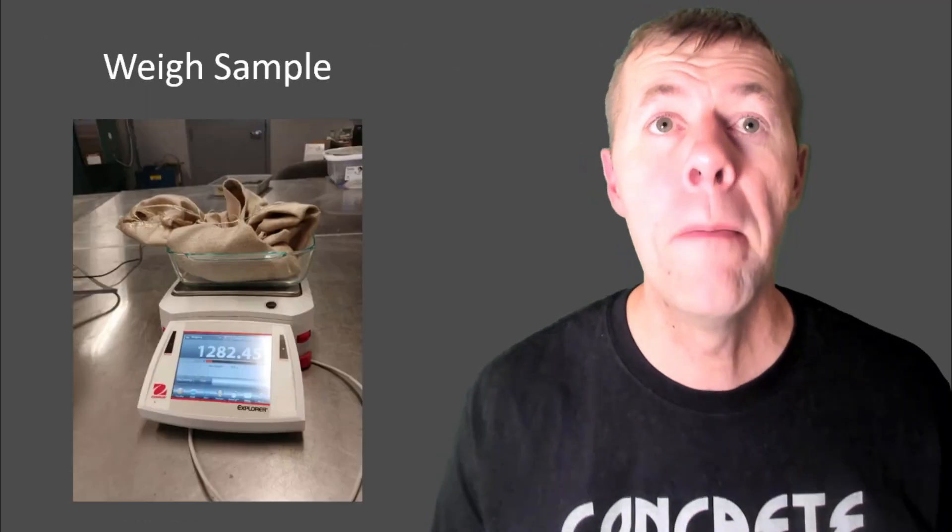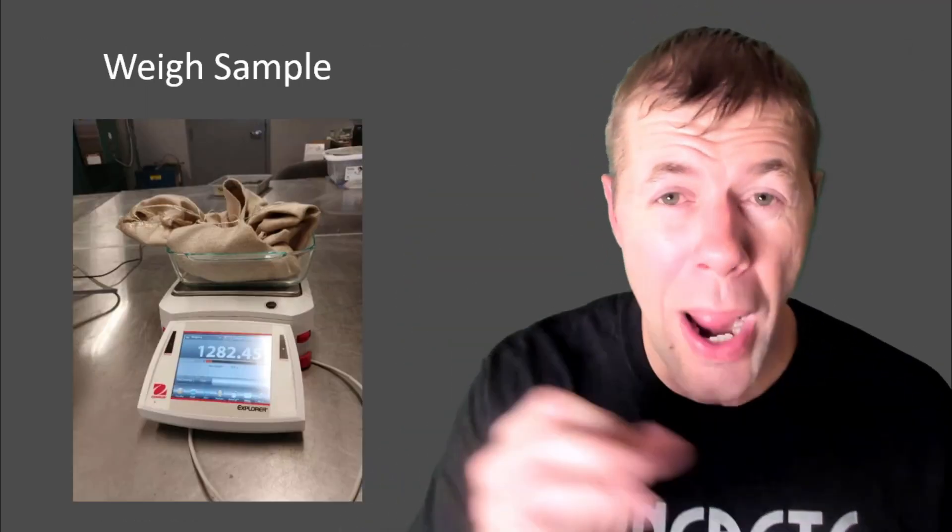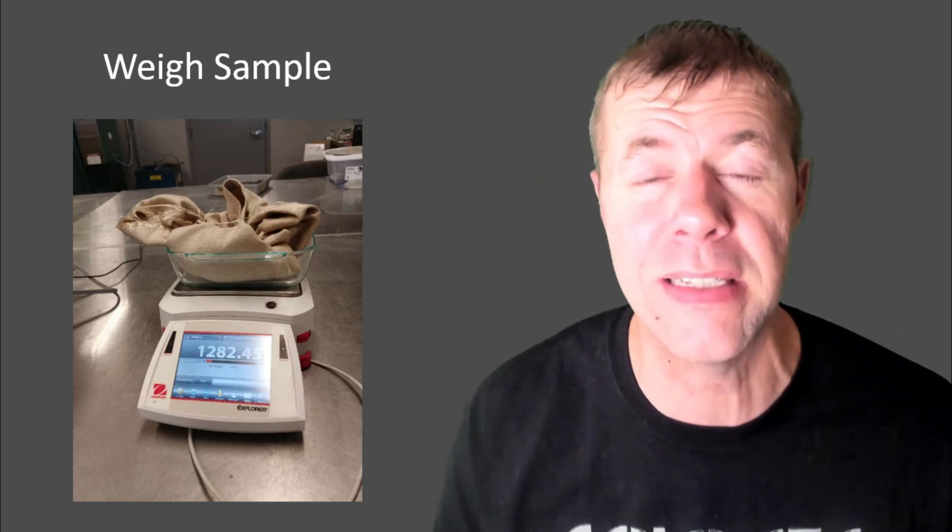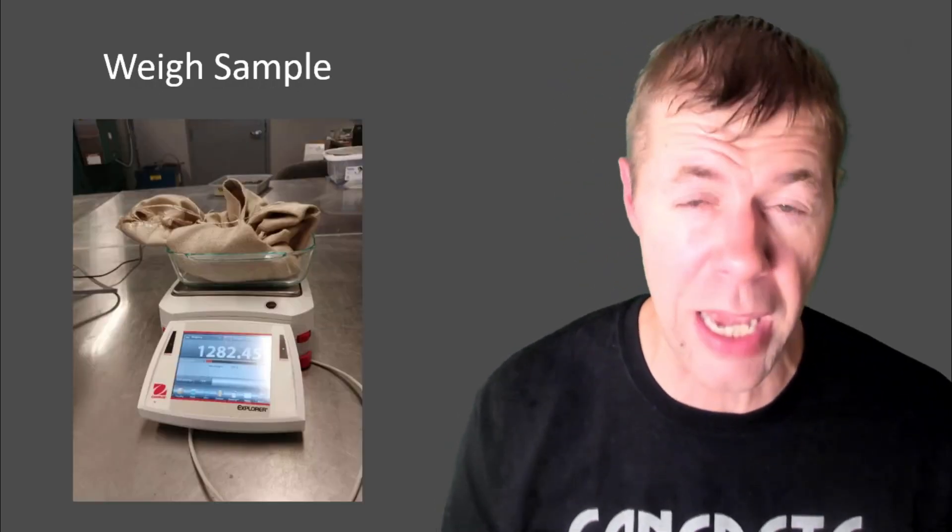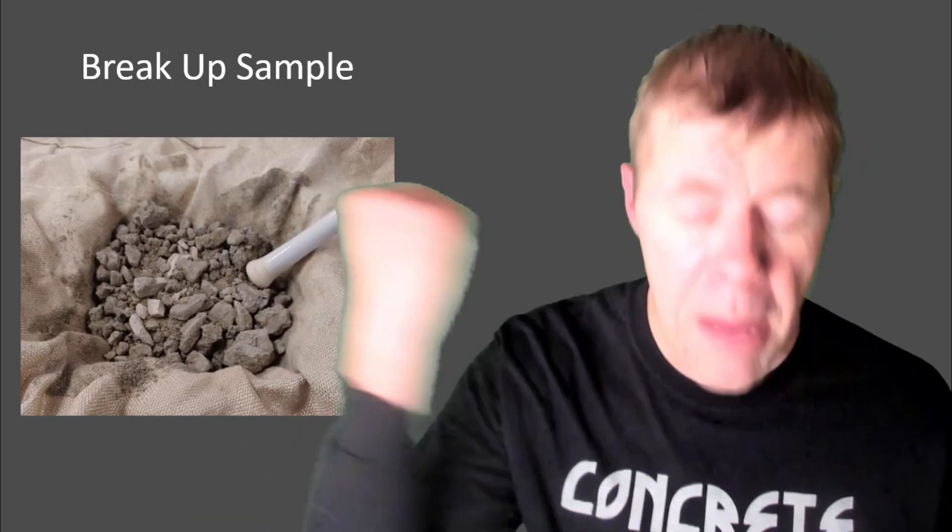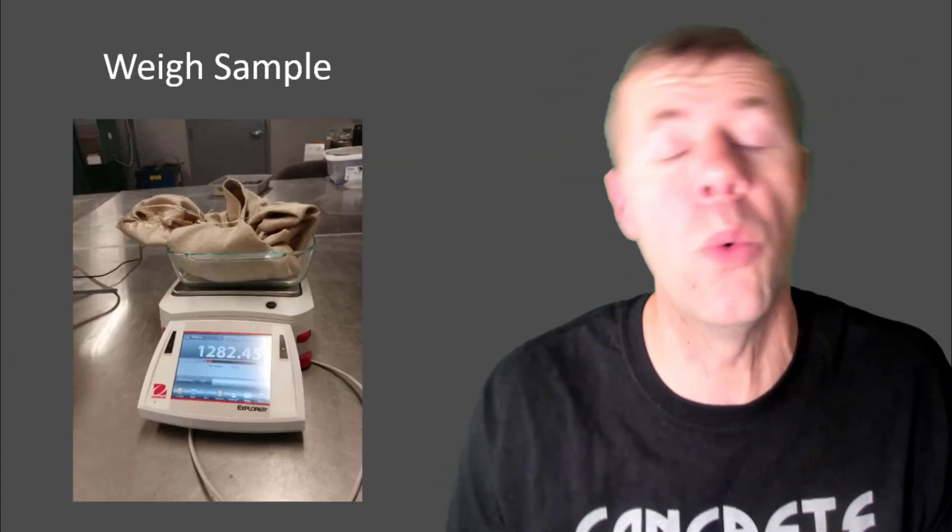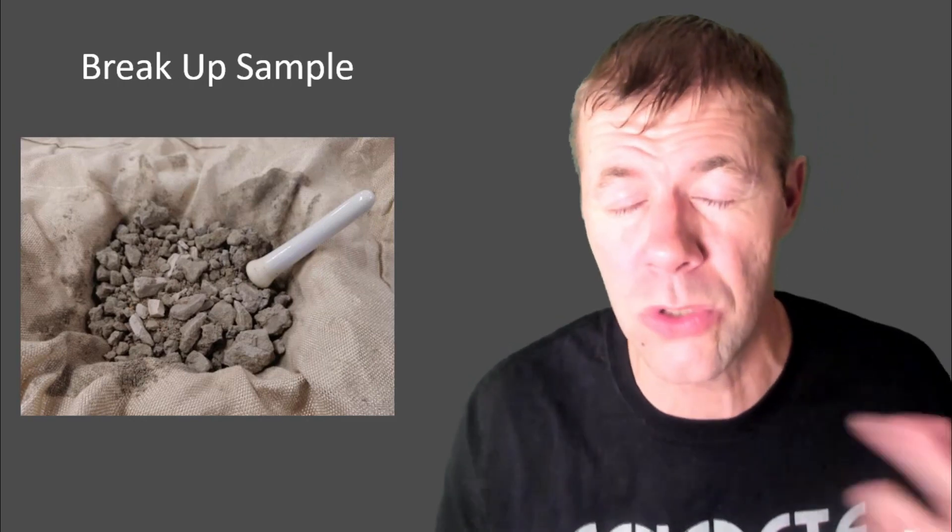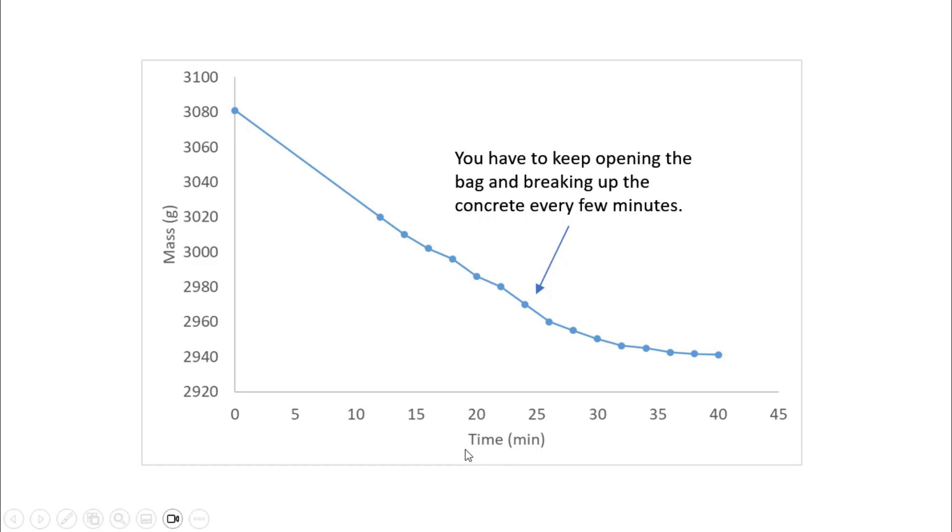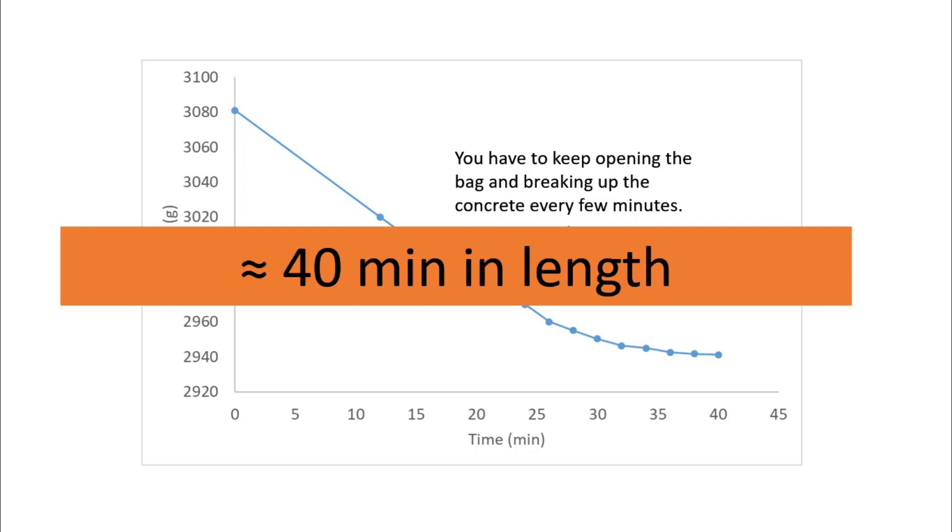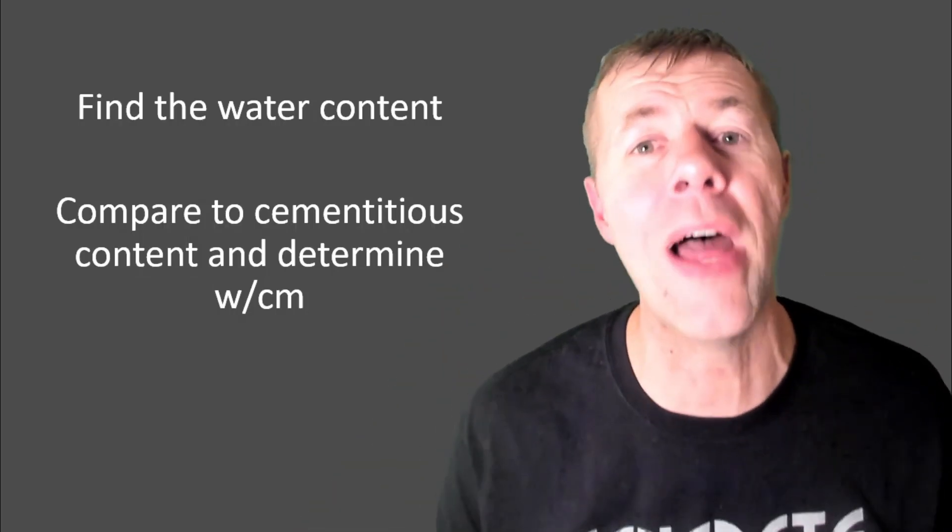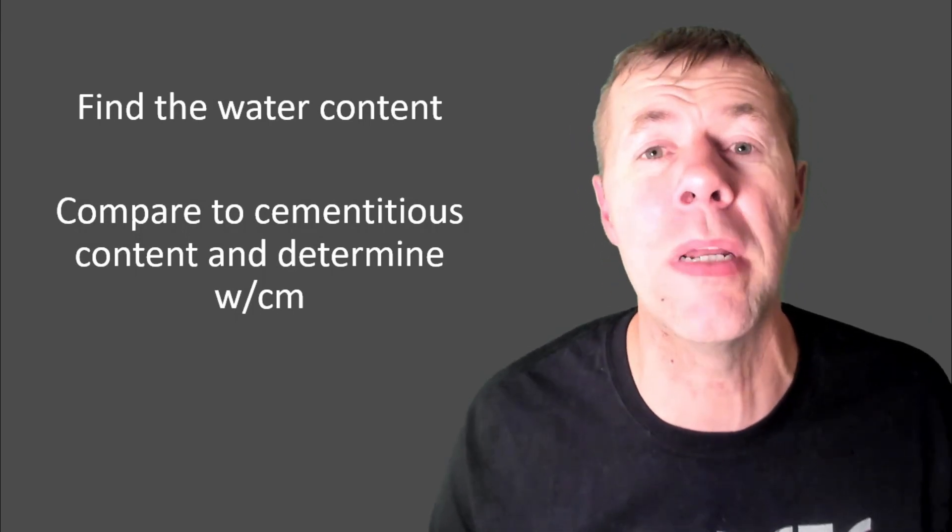But you start out with that wet concrete, and you weigh the sample in this fiberglass bag on a Pyrex dish, and then you put it in the microwave, and you heat it up, and then you take it out, and you weigh it, and then you open up the bag, and you beat the snot out of it because you got to break apart the particles. You put it back together, then you put it in the microwave, then you heat it up, then you weigh it, and then you break it up. I mean, you can kind of see this just goes on and on and on. Yeah, like this graph shows, here is time on the x-axis, every one of these dots is where you had to open it up and break it up as per the test method, and this is the change in mass over here. That's a lot of breaking up. That's a lot of time, takes about 40 minutes at least to measure this sample.